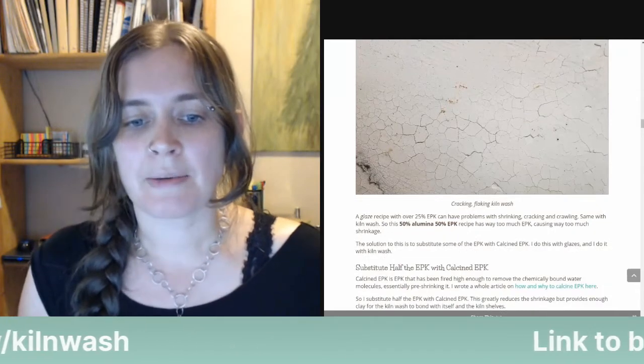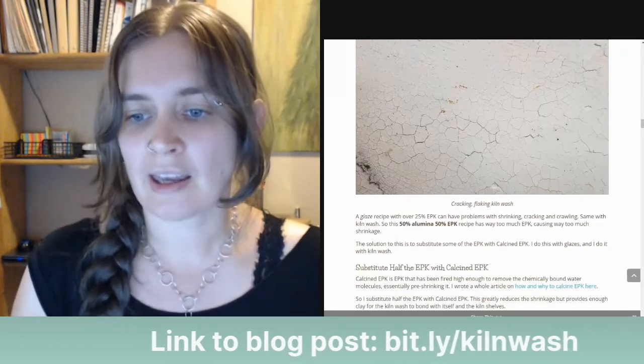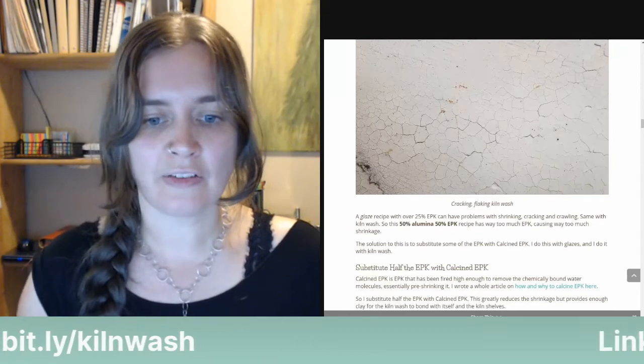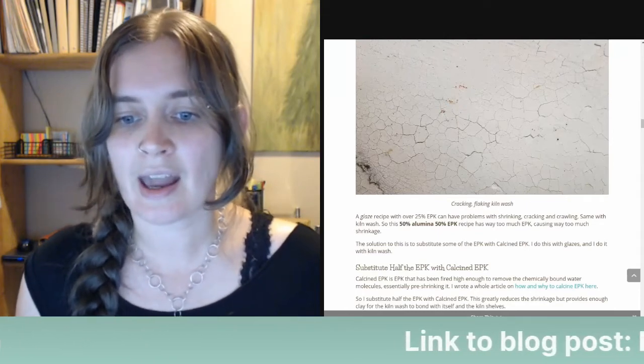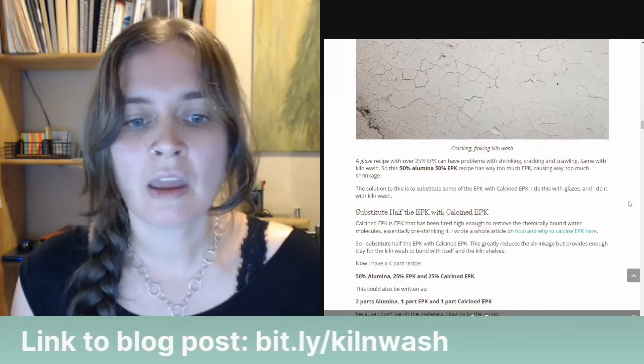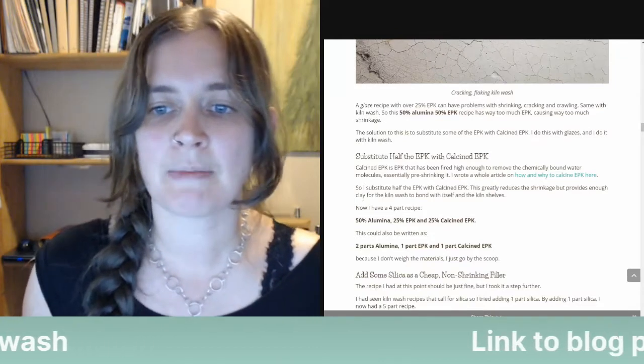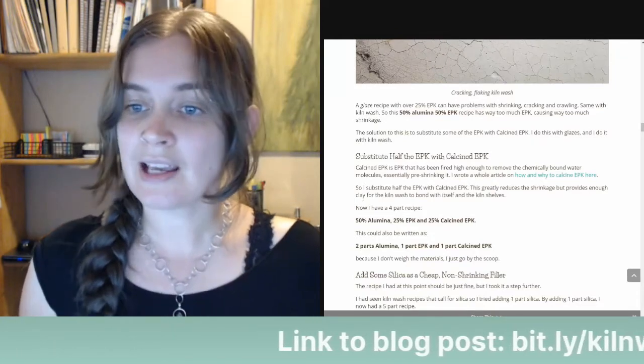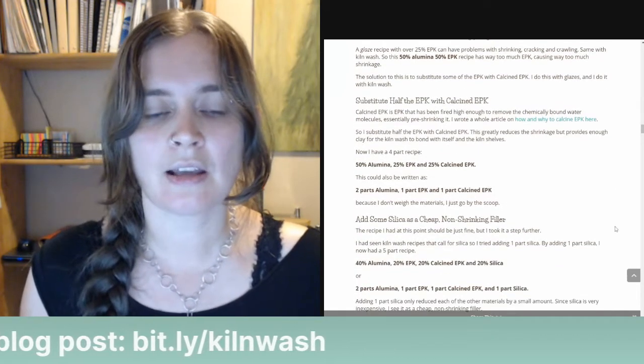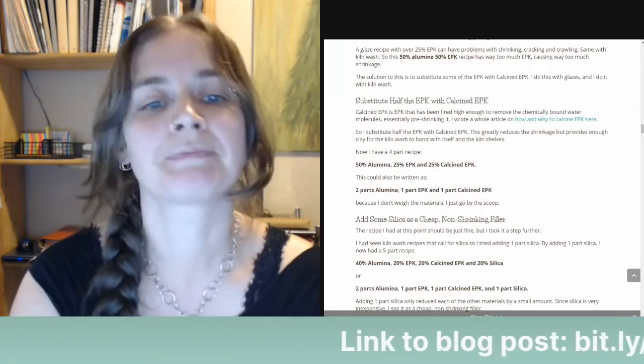A glaze recipe with over 25% EPK can have problems with shrinking, cracking, and crawling. Same with kiln wash. So this 50-50 alumina EPK recipe has way too much EPK, causing way too much shrinkage. The solution to this is to substitute some of the EPK with calcined EPK. I do this with glazes and I do it with kiln wash. So the next step is we substitute half the EPK with calcined EPK.